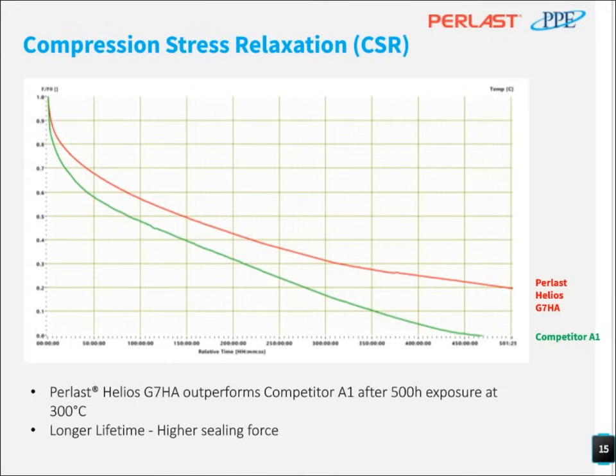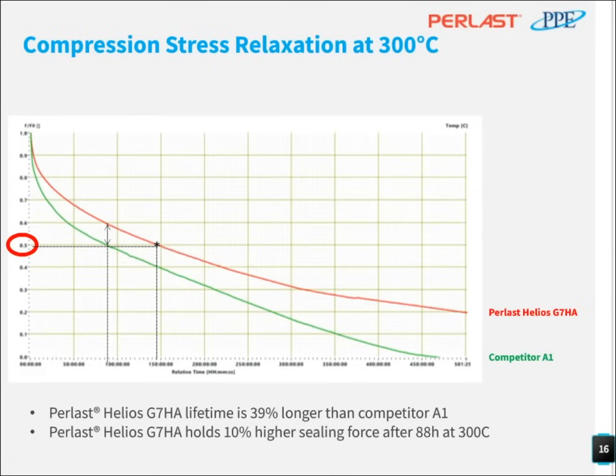So if we compare the times, as I said, in the ISO standards, it says 50% of the time taken as the lifetime of the seal. So if we compare the time to reach 50% of the initial force, as you can see, we offer almost 40% more lifetime than the competitive material.